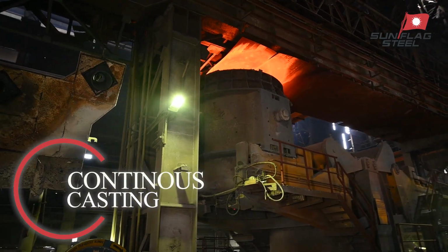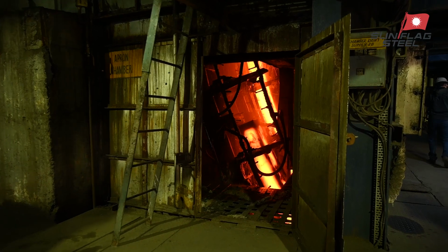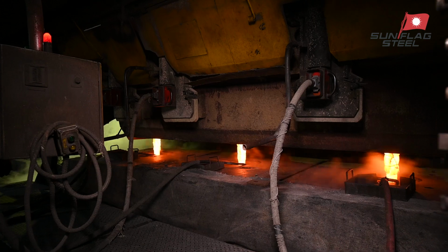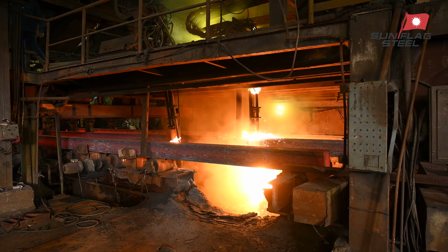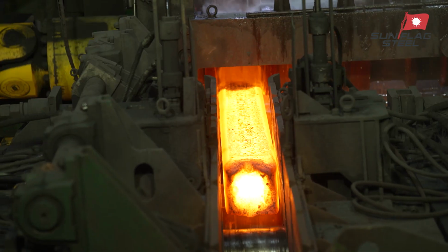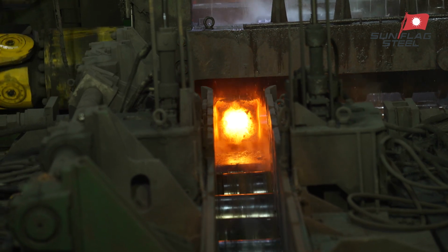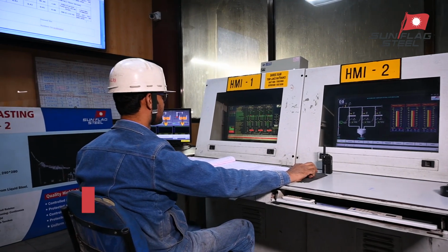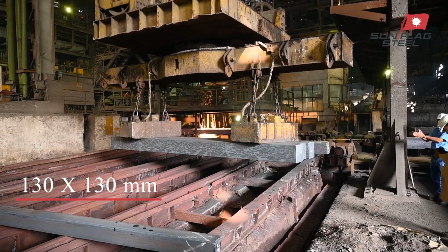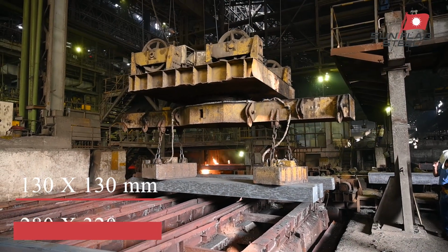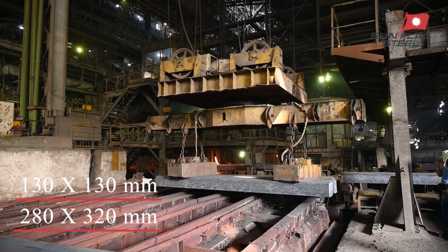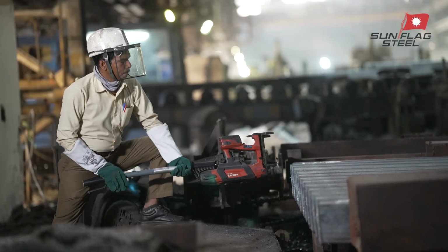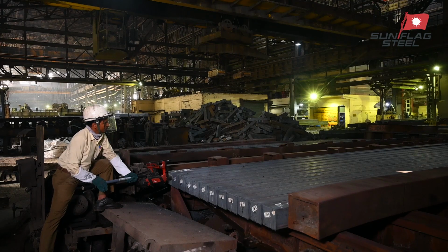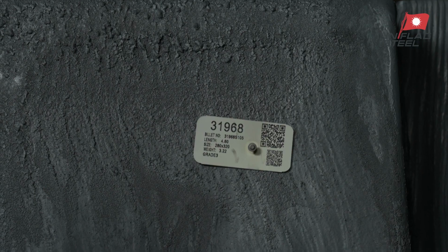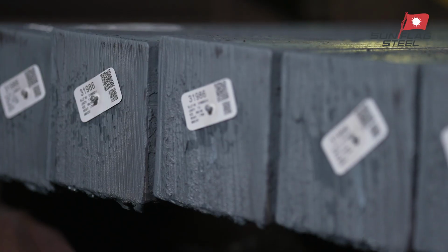Continuous casting. Continuous casting machine casts liquid steel into blooms and billets. Slag sensor ensures no carryover slag from ladle to tundish. Turnover cooling bed ensures uniform properties. We have facility to cast sections from 130 by 130 mm square to 280 by 320 mm square. Each billet and bloom is nailed with a tag carrying heat number, strand number and billet number, ensuring complete traceability in downstream process.